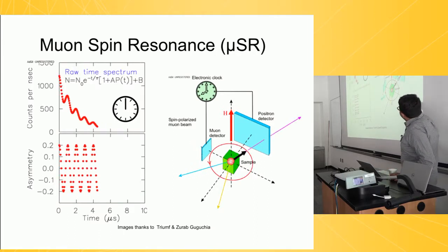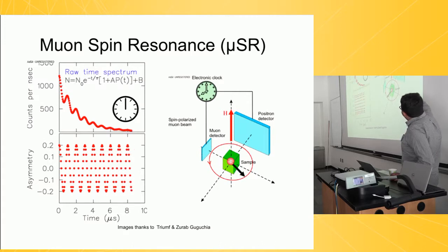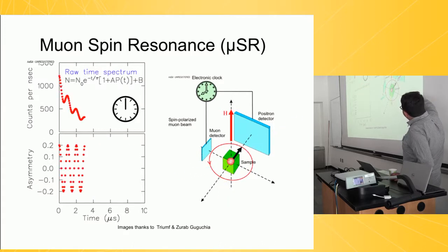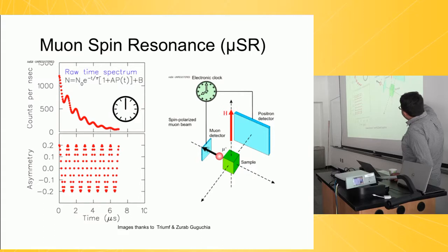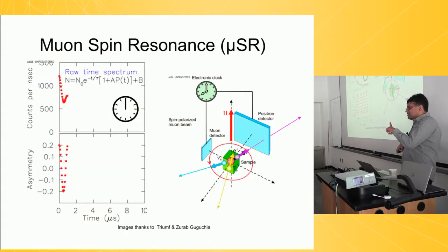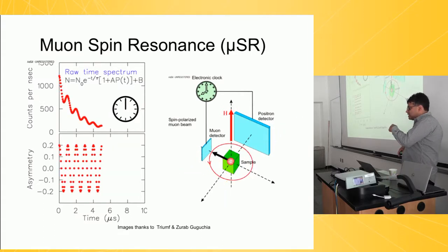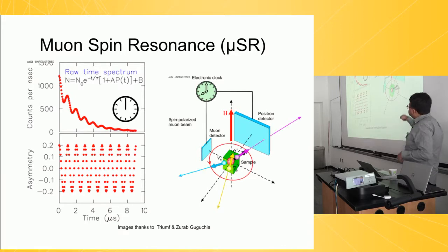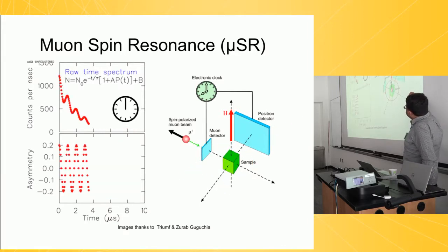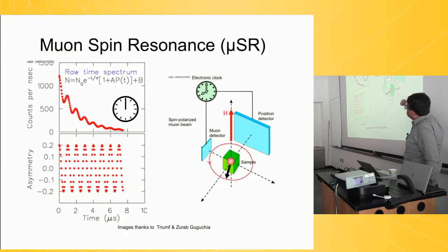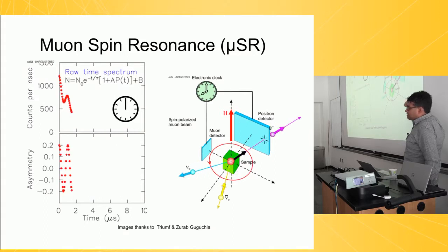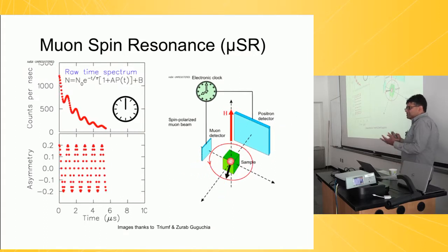A beautiful way to measure magnetism. And in practice, what you do is you measure asymmetry. That's the difference in positron counts between this counter and the counter on the other side. And if your sample has an internal magnetic field, then you expect the muon to precess. And so if you measure that signal as a function of time, what you'll see is beautiful precession. And that precession is a gold standard of magnetism.